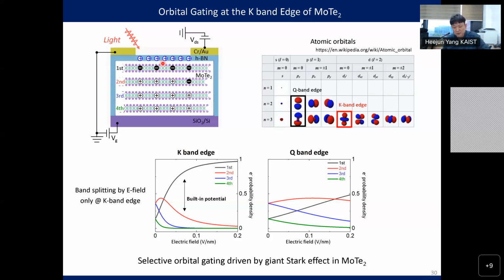So if we have, for example, trapped holes in the hBN, we have accumulated electrons in the first layer, second layer, and if we calculate the electron density function, depending on the layer, the first, second, third, we have some screening. So we have some electrons in the first layer. The x-axis is the electric field, which is applied by the trapped charges in the hBN. For example, here we have some large electron accumulation in the first layer and less electron accumulation in the second, third, fourth layer. So what does it mean? Here, we have a built-in potential or built-in electric field, which is very important for photovoltaic solar cells or other things. So if we illuminate light, we have photocurrent based on these K-valley electrons, not Q-valley. This is the key. That's why I named it orbital gating.